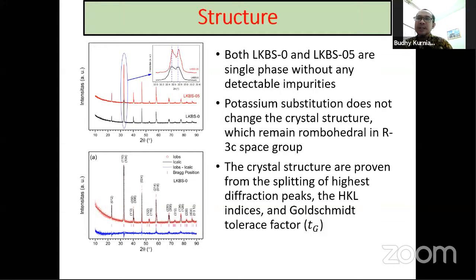In the structure analysis, we use the X-ray diffractometer, and from the XRD result, both our samples, without and with the doping of potassium, are single phase, without any detectable impurities. Potassium substitution does not change the crystal structure, which is rhombohedral with space group R3C. The crystal structure is proven from the splitting of the highest diffraction peak, and from there the HKL index and Goldschmidt tolerance factor can be resolved. Next, please.